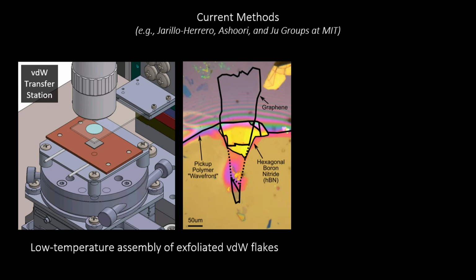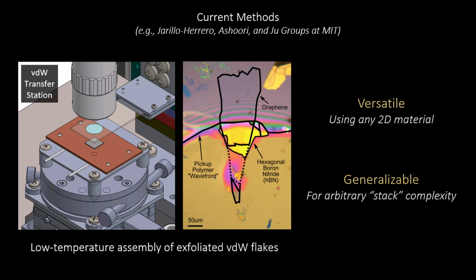So nearly all reports to date have generated these Moiré materials experimentally using a tool called the van der Waals transfer station, which is an exceptional tool of condensed matter research, because it allows me to mix and match, twist and stack 2D materials into Moiré material devices, as used by the Jarillo-Herrero, the Ashoori, and the Ju group here at MIT. So this is an exceptional tool because it's highly versatile. Essentially any 2D material that I can exfoliate down to thin flakes, I can twist it and incorporate it into a Moiré material device.